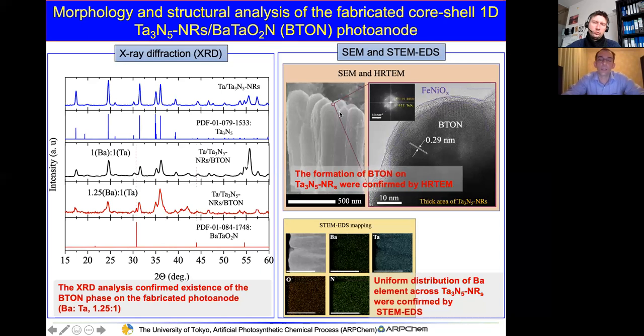So for that reason, the TEM analysis is required, because in the high resolution TEM we can directly see the planes from the materials. By measuring the distances in the plane, it can give us information about whether it's really barium tantalum oxynitride material or not, and also from the diffraction pattern. So the formation of the barium tantalum oxynitride on tantalum nanorod was confirmed by high resolution TEM. And then we use STEM-EDS mapping to show the uniform distribution of the barium element across the nanorod.